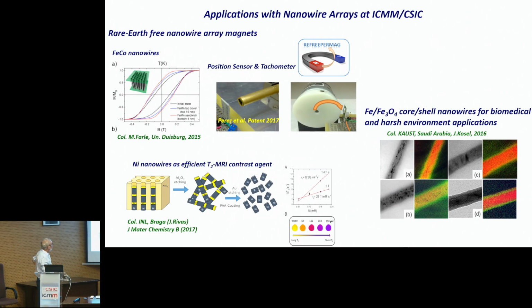Some other applications. So this was in collaboration with a European project. Our task was to fabricate rare earth-free nanowires to be used eventually as alternative magnets. So actually the response is not so high, particularly because of the magnetostatic interactions between the nanowires. But in collaboration with the group of Michael Farle in Duisburg, we were able to increase these properties as magnets. We prepare iron cobalt composition because of the high saturation magnetization of 2.3 Tesla and the high Curie temperature.